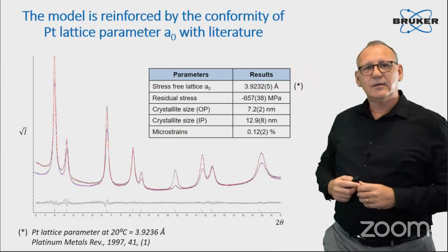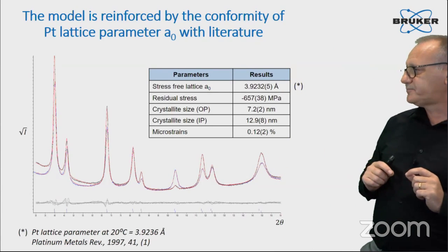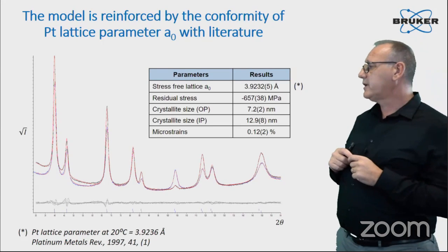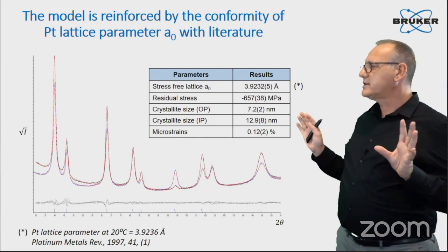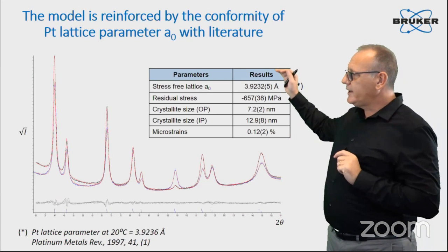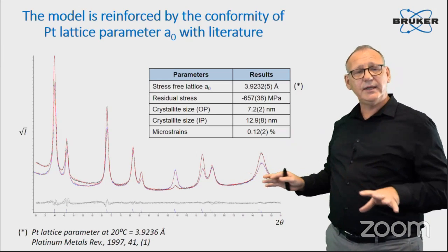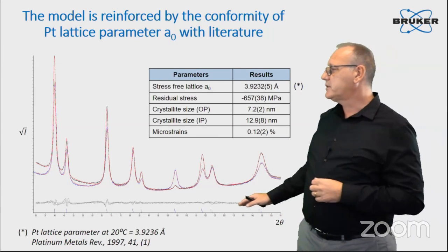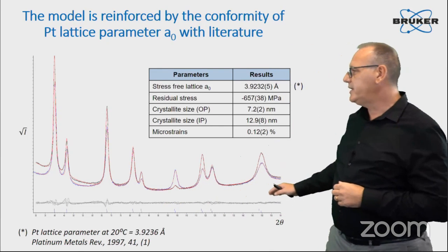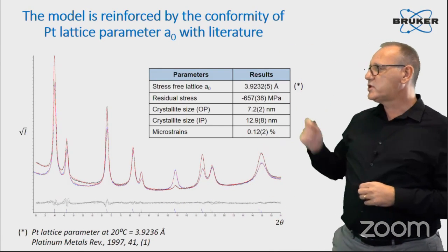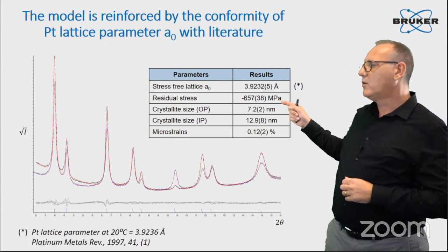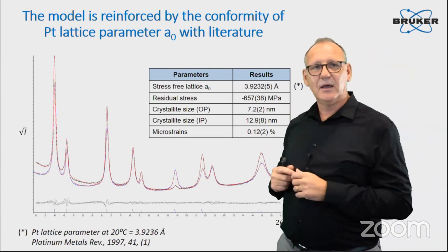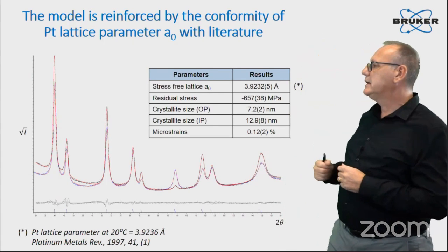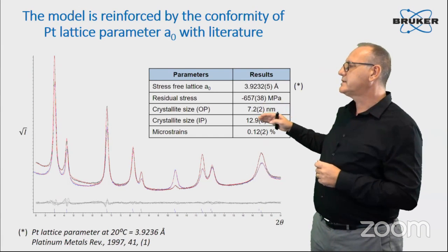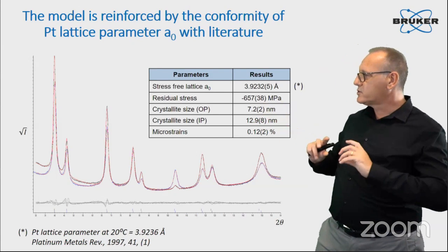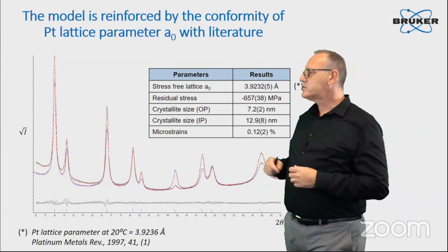And by doing this, we are able to simultaneously, and in a very short refinement time, fit the two curves simultaneously with a consistent model by only refining 5 parameters that will apply differently on the 2 different geometries. The difference plot is extremely good. So we have been able to achieve the right peak position, especially due to the stress. And you see that we have almost minus 700 megapascal, so compressive stress in this material. We have been able to estimate the crystallite size out of plane and in plane. So there is a small aspect ratio here, and the microstrain inside.